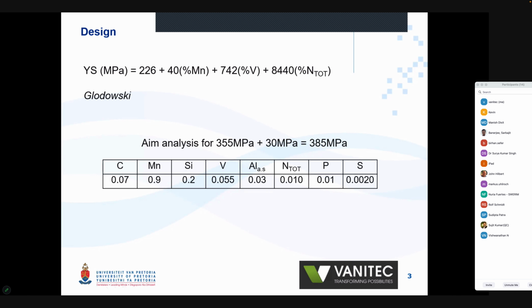A low carbon, 0.9 manganese, slightly lower manganese than normal, and then 0.055 vanadium, and about 100 parts per million nitrogen, keeping the aluminium low, for reasons that have been discussed in previous PPP meetings.